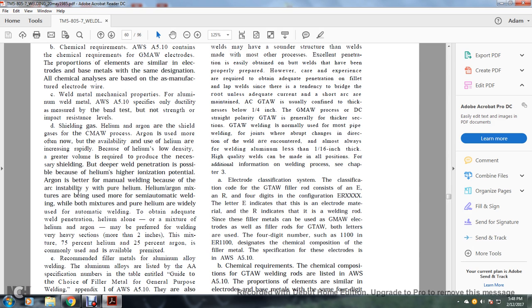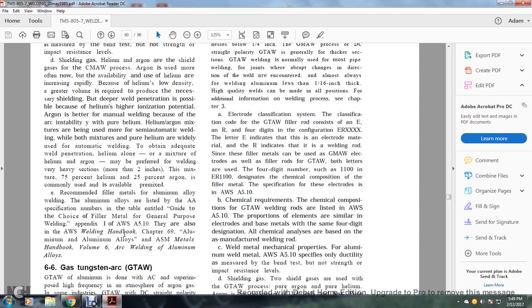Helium-argon mixtures are used for more semi-automatic welding, while both mixtures and pure helium are widely used for automatic welding to obtain adequate weld penetration. Helium alone or a mixture of helium and argon may be preferred for welding very heavy sections more than 2 inches thick. A mixture of 75% helium and 25% argon is commonly used and available premixed.